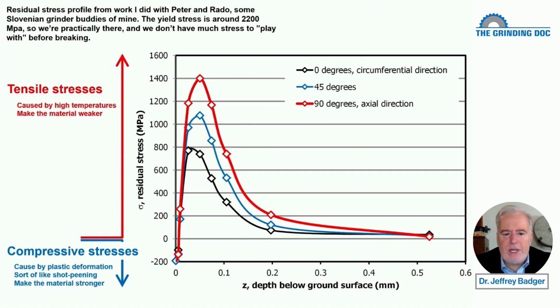But basically, tensile stresses are positive. Positive as in positive numbers, not positive as in good. Here we have tensile stresses in red that went from 400, 600, 800, 1,000, 1,200, 1,400. Darn, we're getting close to the yield stress of the material, so we have a very weak material. And then we have some compressive stresses at the very surface due to plastic deformation, kind of like shot peening. Those are good. Those got down to around negative 200, but it was only at the very surface. And then below the surface, we had the tensile stresses, and those are bad because they caused the workpiece to crack.